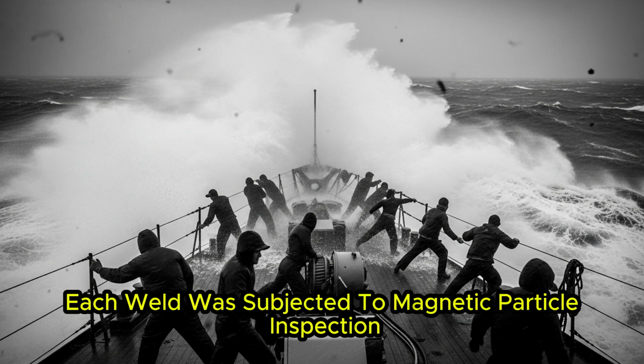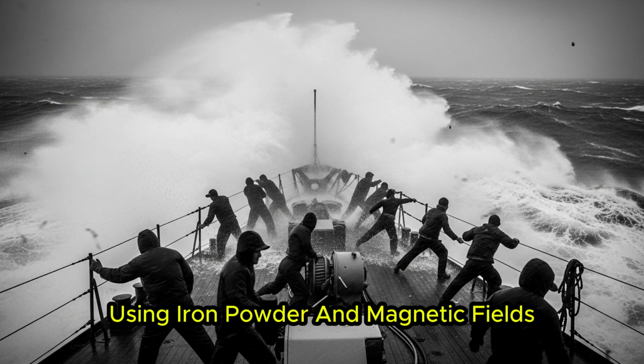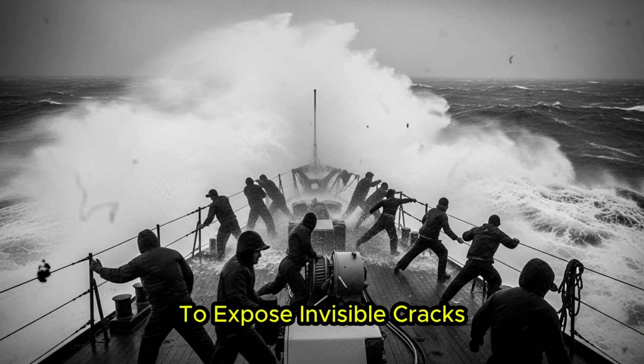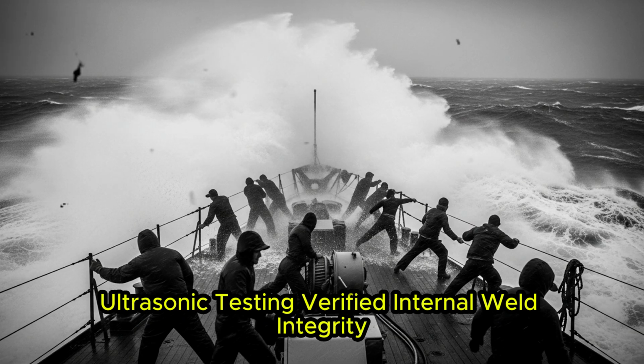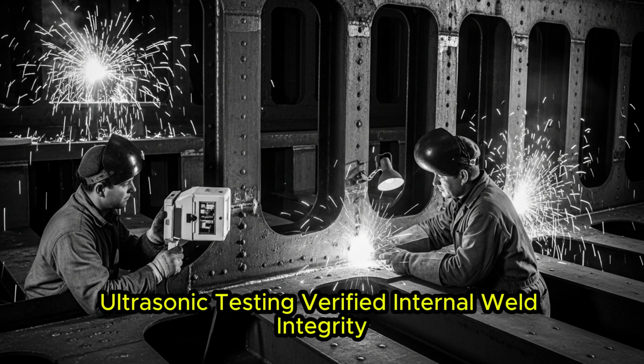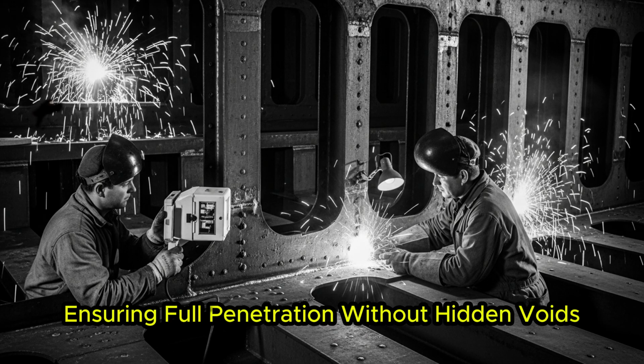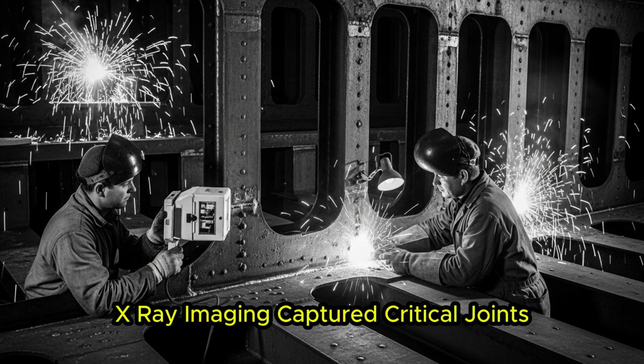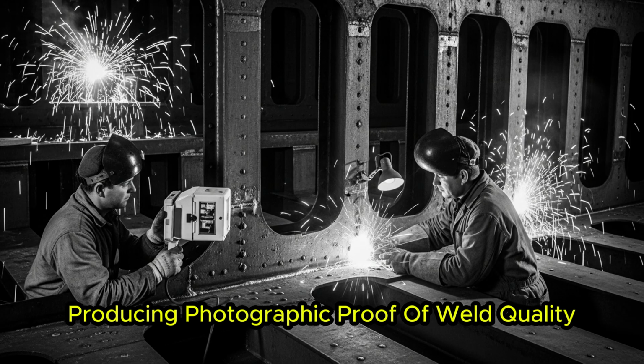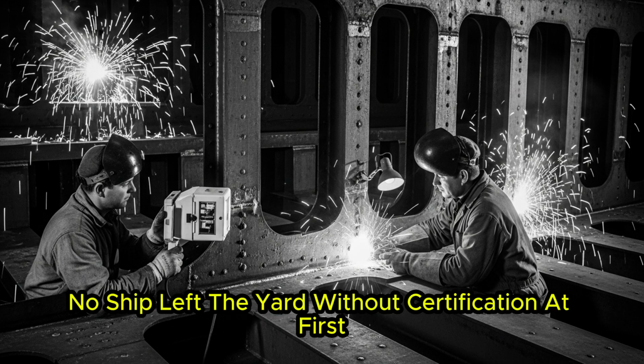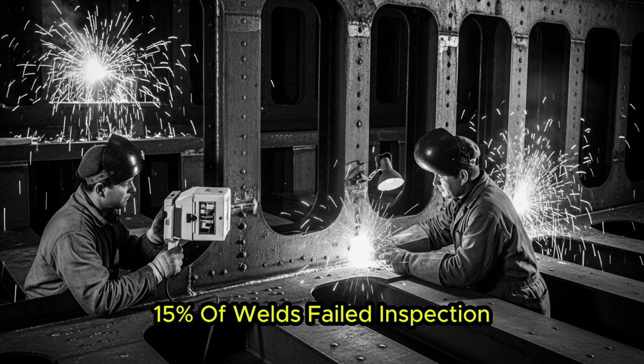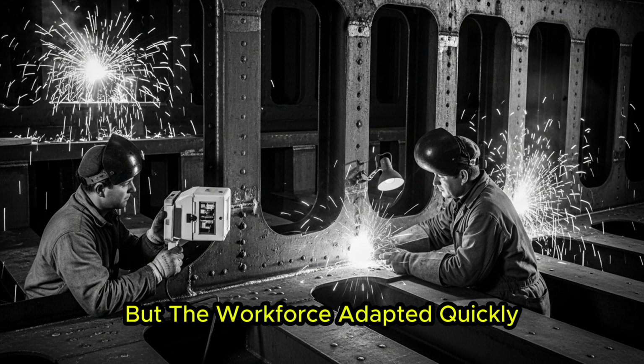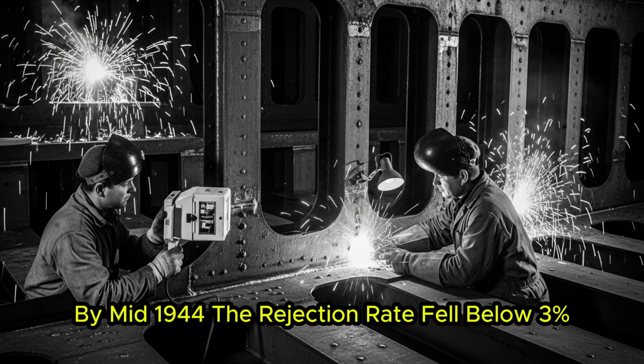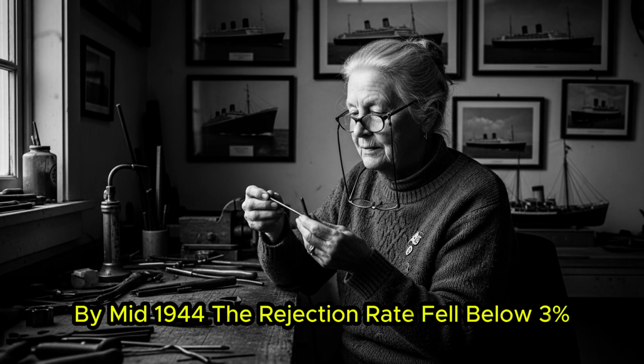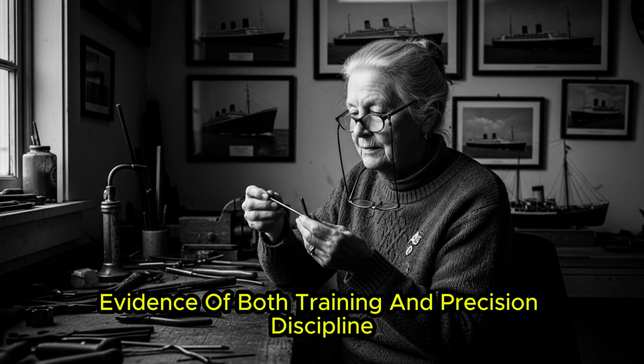Each weld was subjected to magnetic particle inspection using iron powder and magnetic fields to expose invisible cracks. Ultrasonic testing verified internal weld integrity, ensuring full penetration without hidden voids. X-ray imaging captured critical joints, producing photographic proof of weld quality before launch. No ship left the yard without certification. At first, 15% of welds failed inspection, but the workforce adapted quickly. By mid-1944, the rejection rate fell below 3%, evidence of both training and precision discipline.